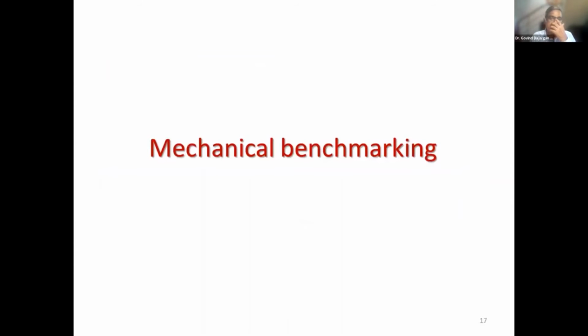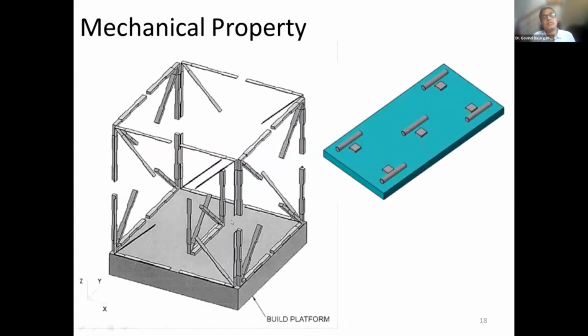In mechanical benchmarking, when we started looking, there were two standards which give us some idea about the mechanical benchmarking. One is AWS D20.1, which says that we should build the test coupons at all the 8 corners of the build volume as well as in the center. It requires building coupons in X, Z, as well as 45-degree direction, and also thick and thin. Thin coupon will be of the order of 1 mm thickness, and thick will be 6.5 mm thickness or higher. So with that, we generate data based on the location, thickness and direction of the sample, to see what kind of scatter we get in the property.